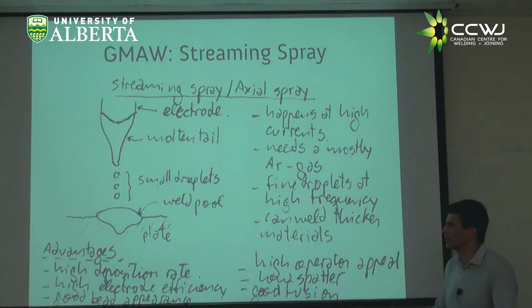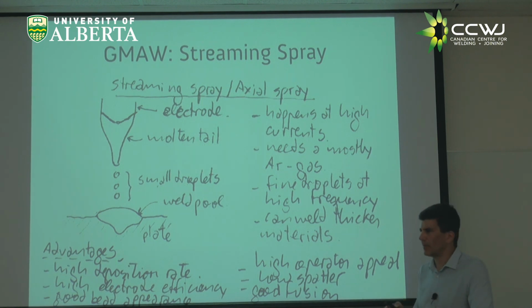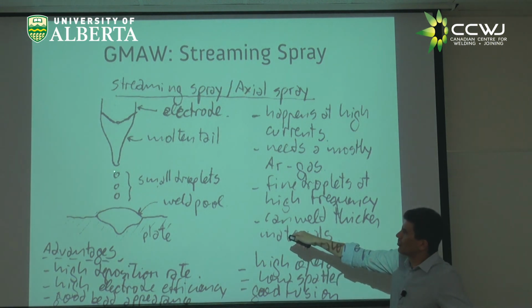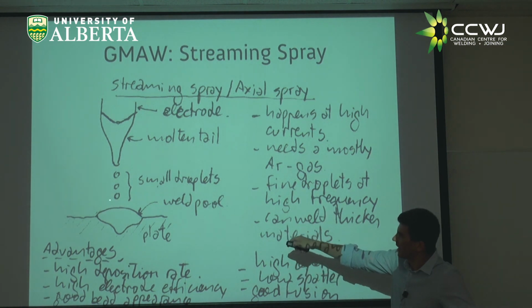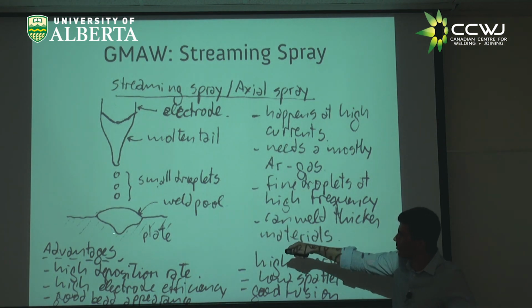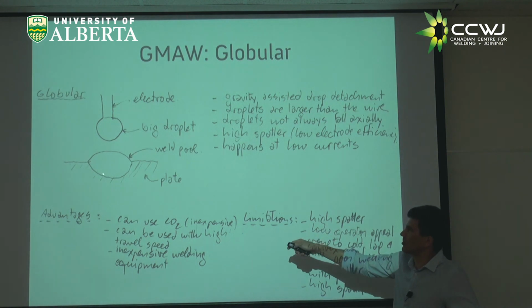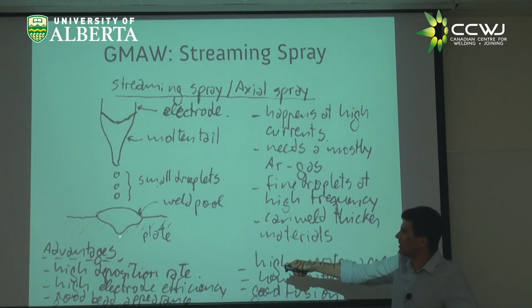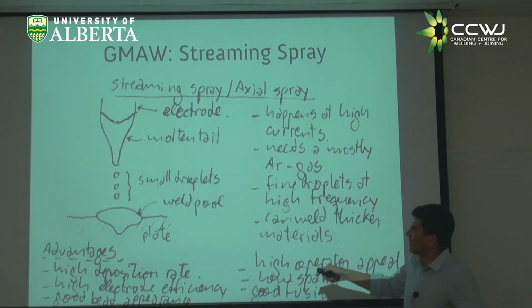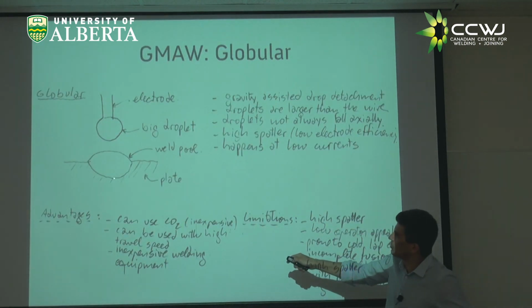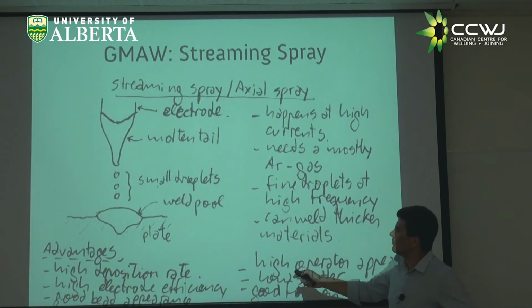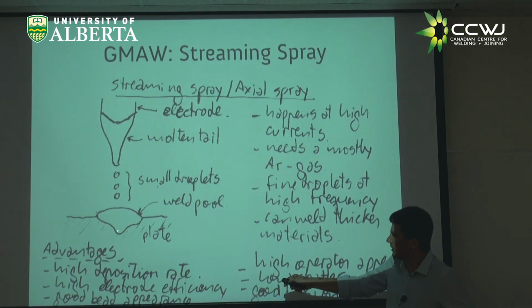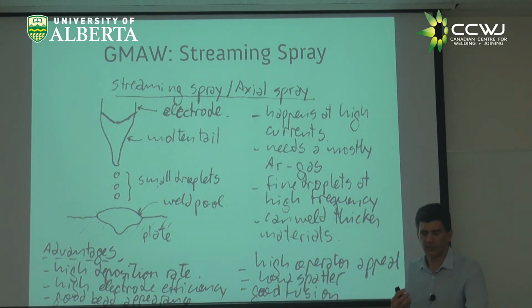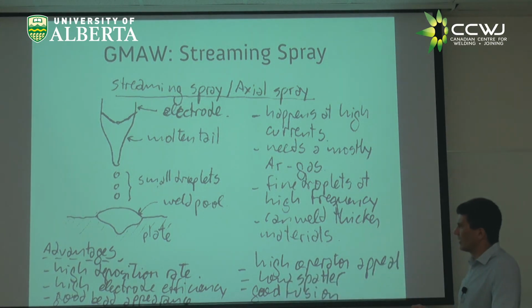Now, if you have high current, right, you have lots of power to melt the base metal. But also, these droplets are coming fast, and they act like they're going straight to the bottom, like cannonballing here very quickly, and they give you this type of penetration. So if you look here, this would be what a typical penetration is in globular. Here is a typical penetration in spray transfer. So just think of this. If you wanted this penetration, you needed to melt all this, you needed to put lots of heat. But here, if you wanted this penetration, you put a little bit less heat, right? You save from melting all this part here and all this part there, right? So you can have this high penetration with more efficiency.